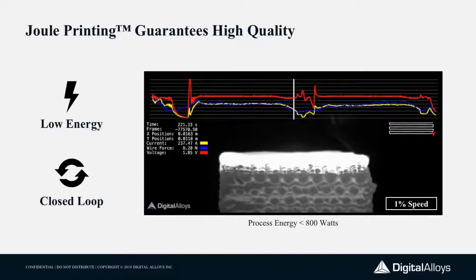It's in an inert atmosphere, argon. And so it's also very low energy compared to DED processes. Here, if you can squint and see, we're operating at about 2 volts across the wire. So, an AA battery of voltage, but high amps, so around 300 or so amps. But you do the math, voltage times current is power. At about 600 to 800 watts, we're forming parts at a couple kilograms an hour of titanium, which is another order of magnitude lower in energy than the typical welding process.